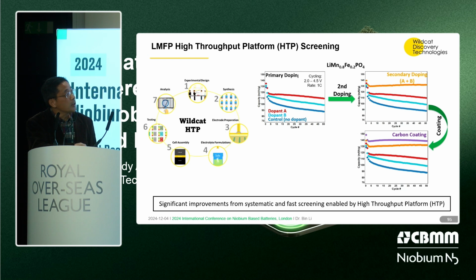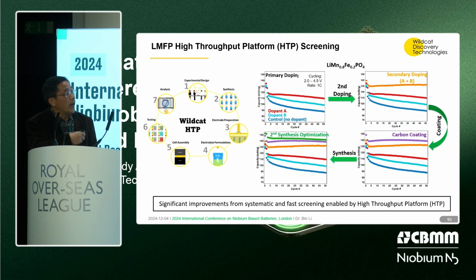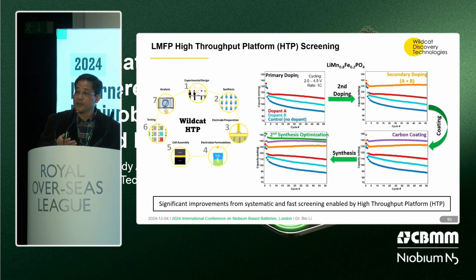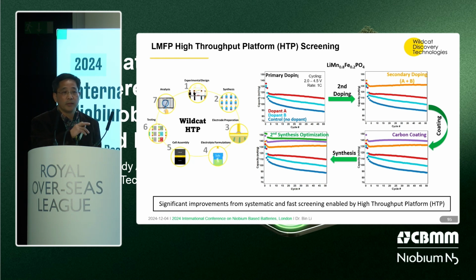With this high throughput platform, after you lock down the compositions and the carbon coating, you want to fine-tune the synthesis condition to make the material. Here, we do further optimization by optimizing the synthesis condition. You can see you get a further improvement in both capacity and the cycle life. So this is showing how this high throughput platform works. And we can work with different customers for the battery materials development.